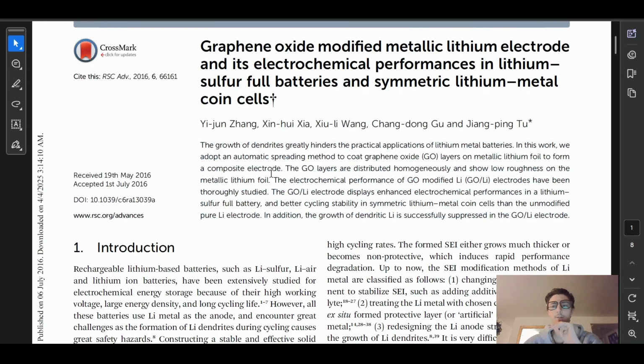This is like a nice summary of the whole paper. The paper is 8 pages. 2 pages are references and stuff, so around 6 pages. So the growth of dendrites greatly hinders the practical applications of lithium metal batteries. In this work, we adopt an automatic spreading method to coat graphene oxide (GO) layers on metallic lithium foil to form a composite electrode. The GO layers are distributed homogeneously, and show low roughness on the metallic lithium